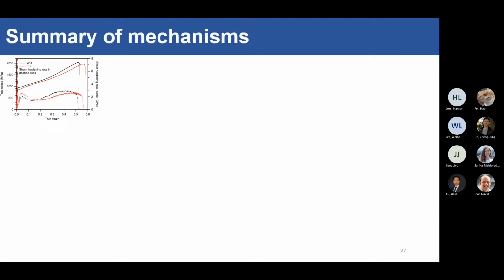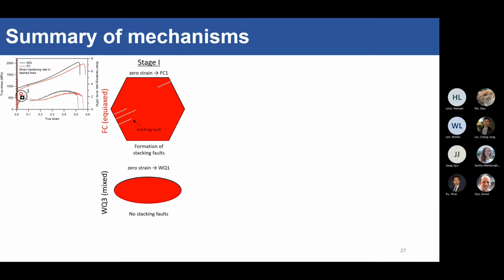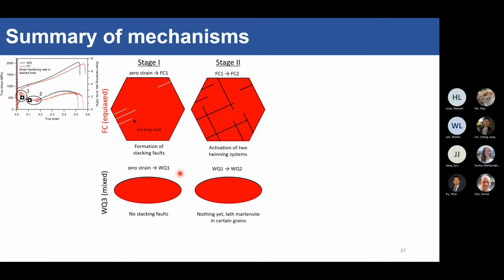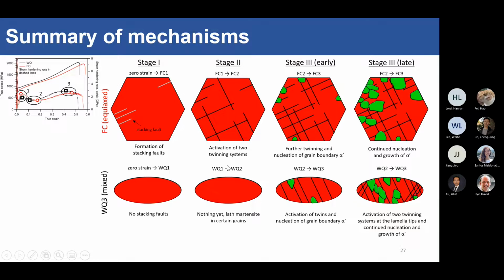And let's summarize if you're a bit lost with all the TEM, I summarized it very nicely for you in the diagram. So in stage 1, we have stacking faults in the FC steel, nothing really much going on in the water quench one. The next stage, you have very nicely established two twinning systems in the FC steel, but again, nothing much going on in the water quench sample. And in stage 3, you start to get your martensite growing off the grain boundaries here, and then they work their way in with increasing strain.